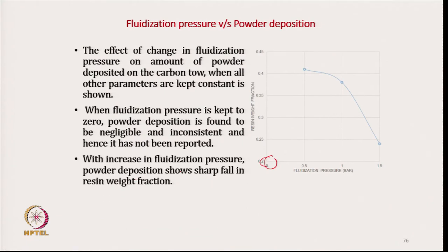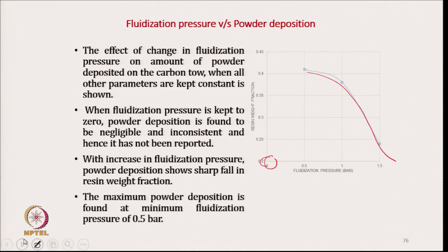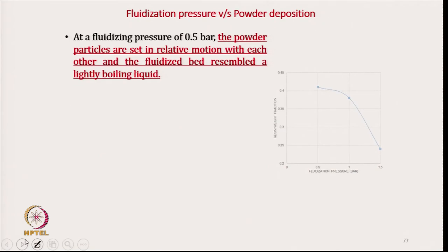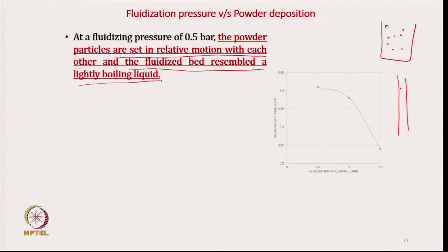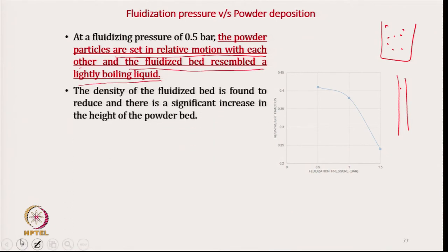With the increase in fluidizing pressure, powder deposition shows a sharp fall. In the weight fraction, the maximum powder deposition is at 0.5 bar. At a fluidizing pressure of 0.5 bar, the powder particles are set in relative motion with each other, which helps in conveying the powder up to the tow. The fluidized bed resembles lightly boiling liquid, the density of the fluidized bed is found to reduce, and there is a significant increase in the height of the powder bed.